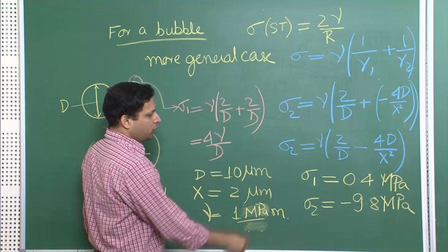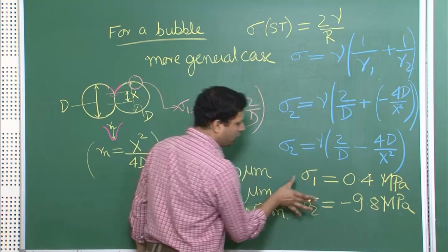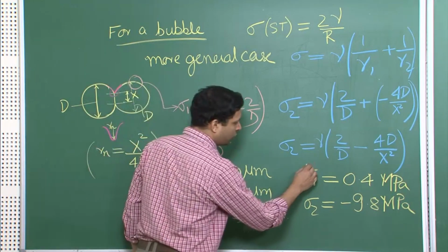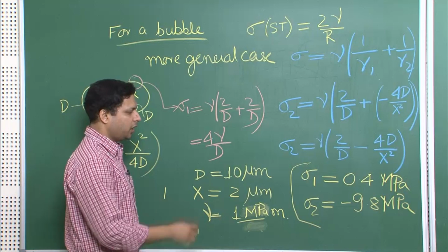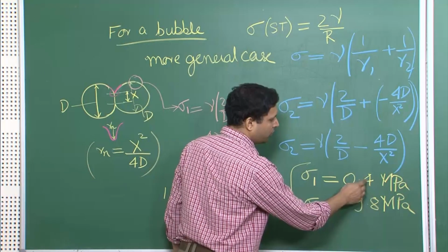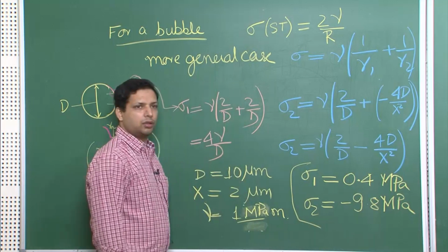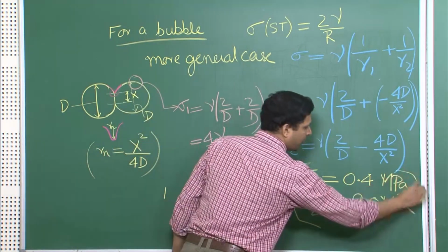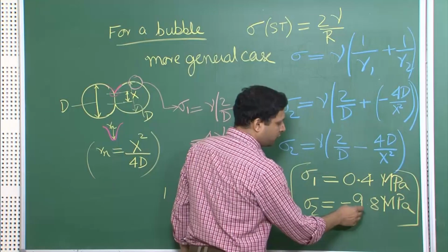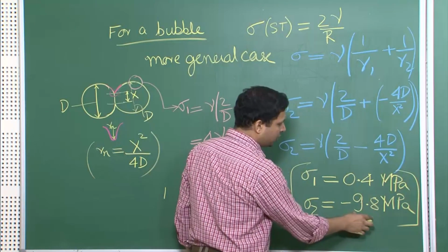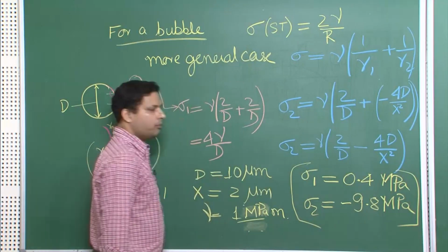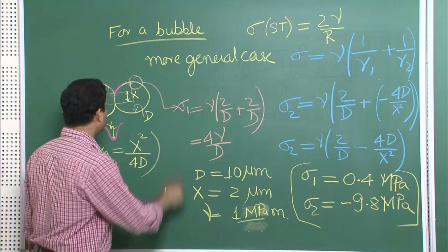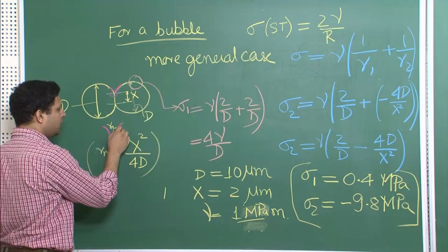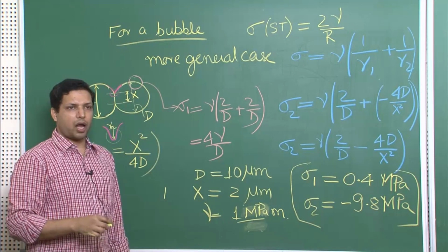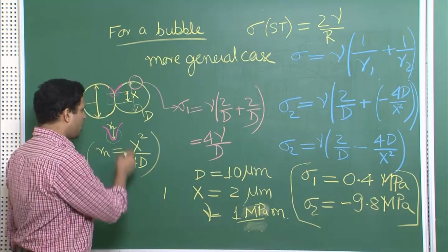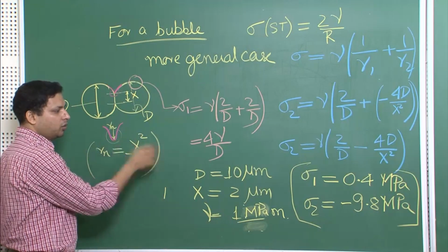Why are we trying to do all this calculation? It becomes clear when you look at the relation or the relative values. What is the sigma 1 value? It is a comparatively very small number, 0.4 megapascal. What is the sigma 2 value? You see two things. One, it is in magnitude very large and it is negative. So, there is a compressive stress that is going on over here. So, in this particular neck region you would see some compressive stresses, and that compressive stress is very large, and the magnitude as you see is very large.